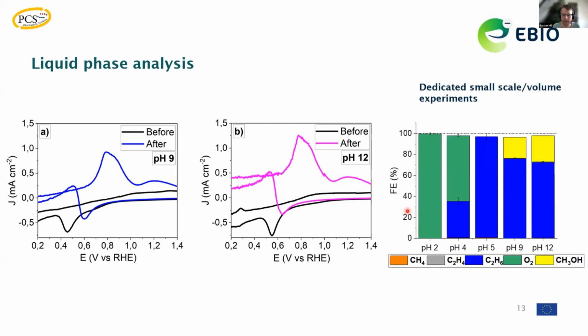So to fully confirm that there's actually methanol being formed in the process, we did some dedicated small volume experiments where we could see that indeed for pH 9 and pH 12, the overall Faradaic efficiency calculated for the process was closer to 80% for ethane, and we formed quite significant fractions of methanol in the end. And that's exactly where we think is this kind of turnover behavior from the high Faradaic efficiency to ethane after a certain period of time, and then liquid products are formed. So in the end, this is very well in agreement with what has been stated also by Sigi, that at a high pH, you do have favorable non-Kolbe product formation.